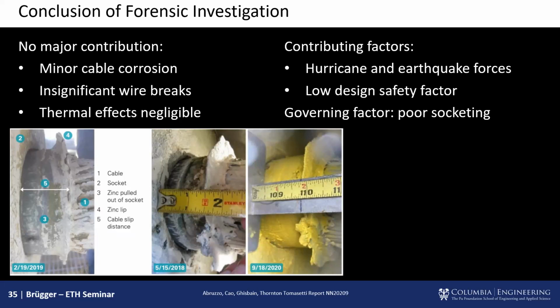And there was a low design safety factor up front. But ultimately, what killed the system is that the brooming of the wires, the socketing, was not done in a methodical fashion, and that the inspection team did not understand that seeing this much extrusion, this is actually the cable failing slowly. This much extrusion of zinc out of the socket is a massive alarm sign, and it was also in the standards to be known that if you're losing more than 1/6 of the diameter of your whole system, then you're essentially in progressive failure.